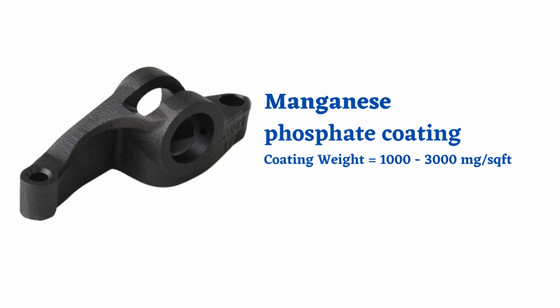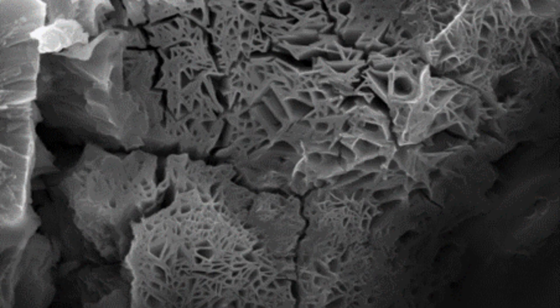Heavy zinc phosphate coating and manganese phosphate coating exhibit a lot of pores on their thick layers deposited on the metal. Though they are not suitable for painting due to their more porous and rough surface, the heavy phosphate treated metal surface is ideal for oiling, waxing and lubrication, and hence such type of heavy phosphating is employed on the metal components where painting is not required.